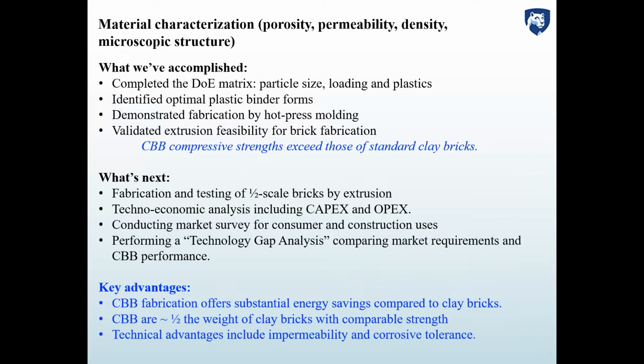So what we've accomplished: we've completed the DOE matrix for particle size, loading, and plastics. We've identified optimal plastic binder forms according to appropriate applications. We've demonstrated fabrication of hot press molding. We validated extrusion feasibility for brick formulations.